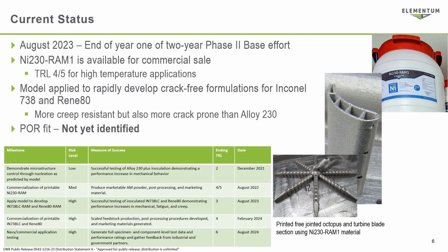It's something of a holy grail to be able to print turbine blades directly because of traditional casting processes that are very time-consuming, laborious, expensive, and have very low yields. Ultimately, the printing of these components will also allow for design improvements that dramatically improve the performance over castings. We have already seen some success in reducing or even eliminating the cracking in Inconel 738 and Rene 80, both of which are even more crack prone without the RAM additions than alloy 230.